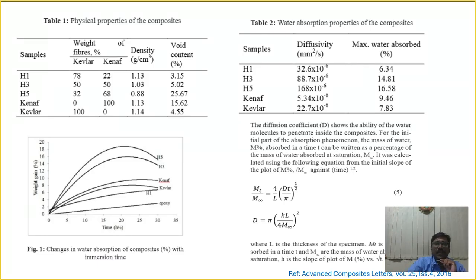volume fractions. H1 has only a small amount of water absorption, 6.34, while H3 and H5 have a higher water absorption rate. It depends upon the volume fraction of the various material contents. And Kenaf and Kevlar have only 9.46 and 7.83 water absorption. Now the diffusion coefficient is also going to be calculated.